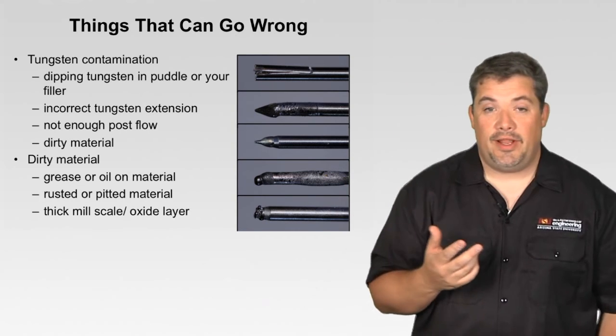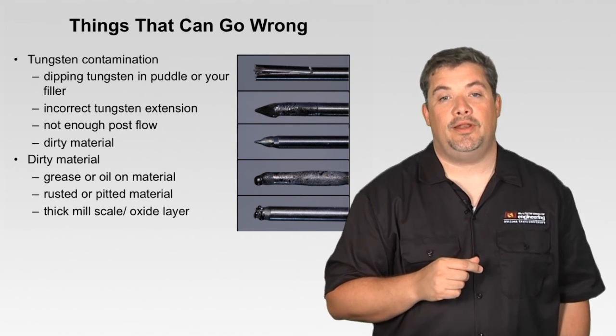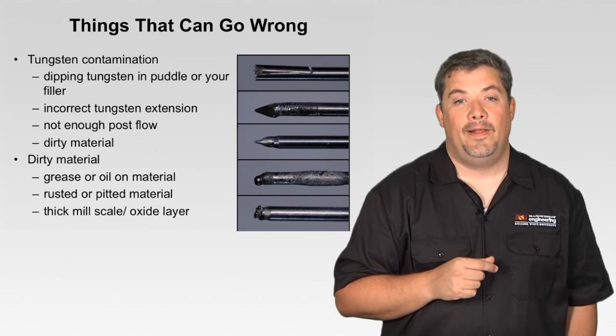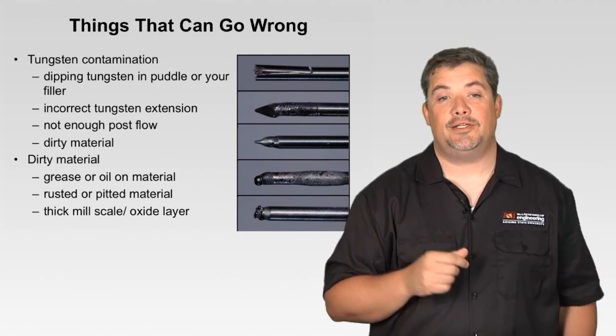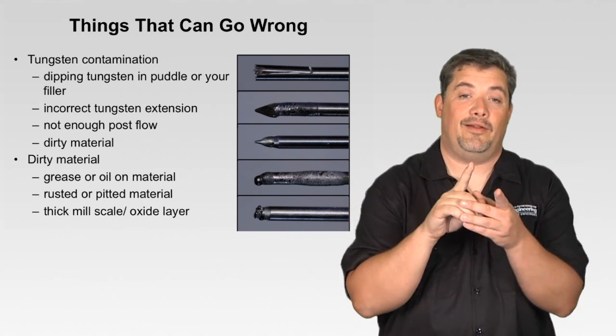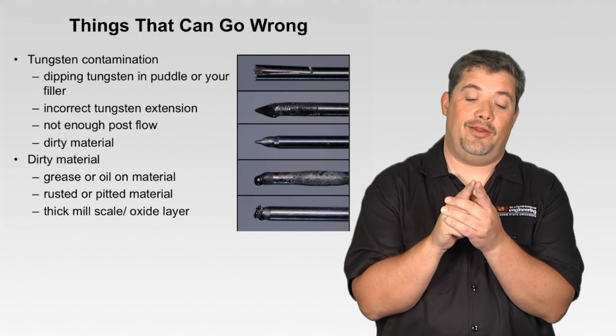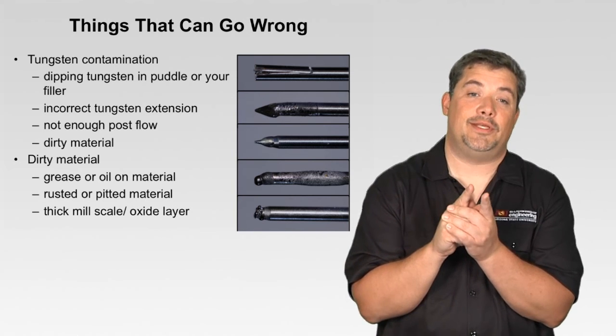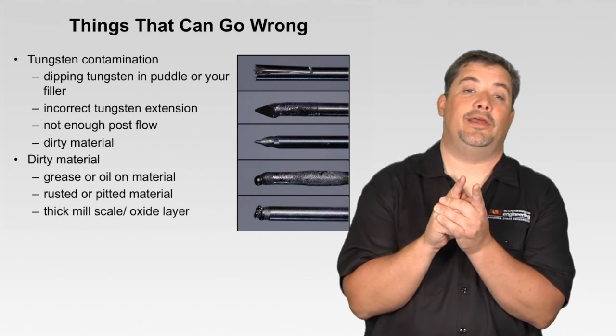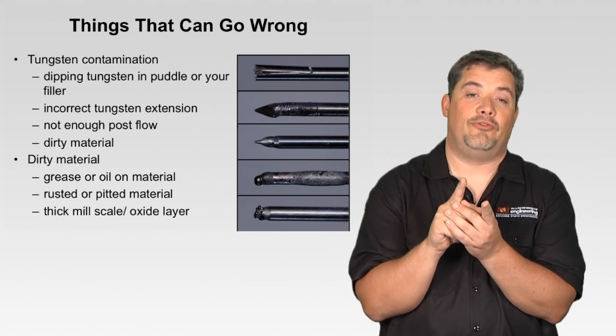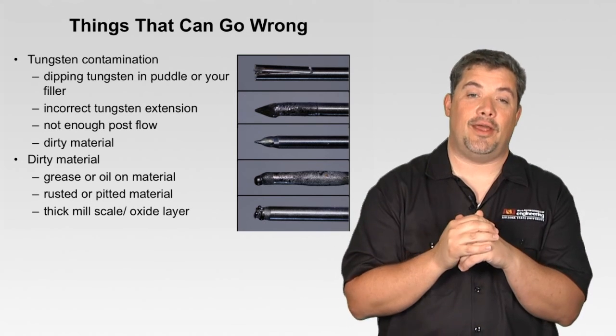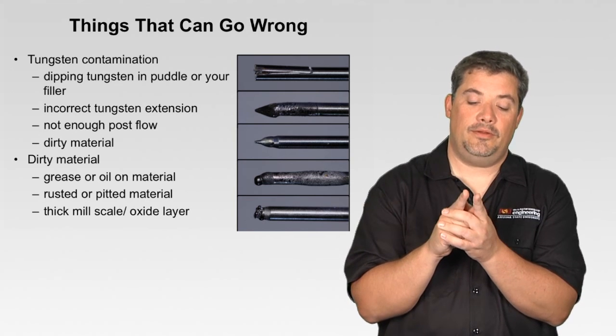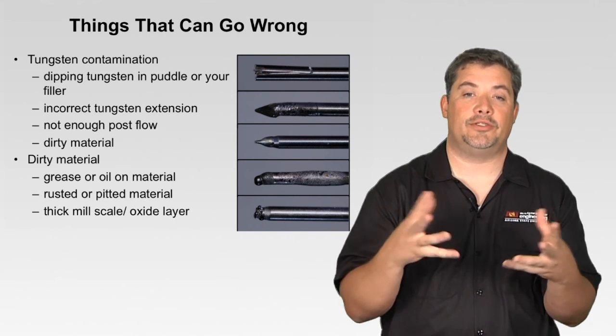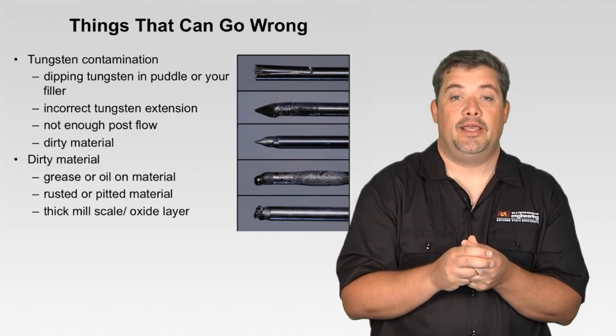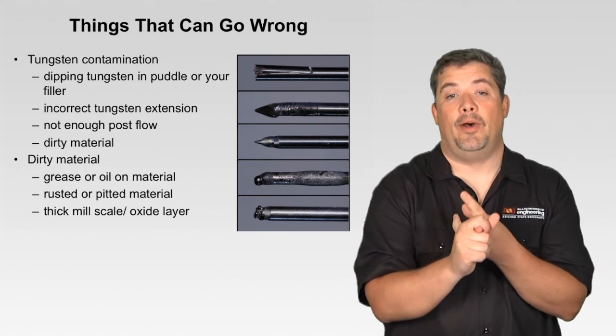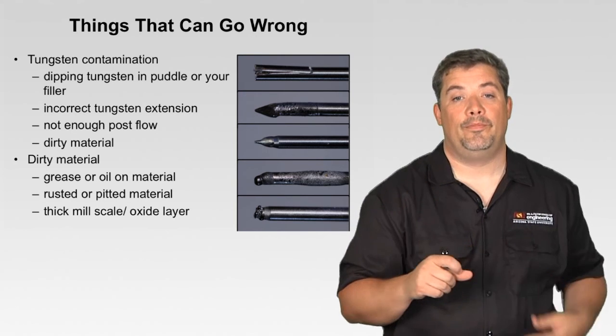Tungsten contamination can be bad news: dipping your tungsten in the puddle or your filler rod. Incorrect tungsten extension, so how far you're sticking it out from the gas nozzle. Typically you don't go more than 3 times the electrode diameter out of that gas nozzle. Any more than that, you're starting to get too far away. There are certainly exceptions to that rule, but you don't want to stick that tungsten out too far or you start to lose how much shielding gas is protecting not only the tungsten, but your weld pool.